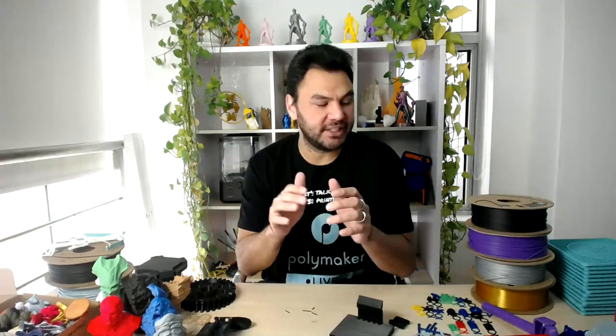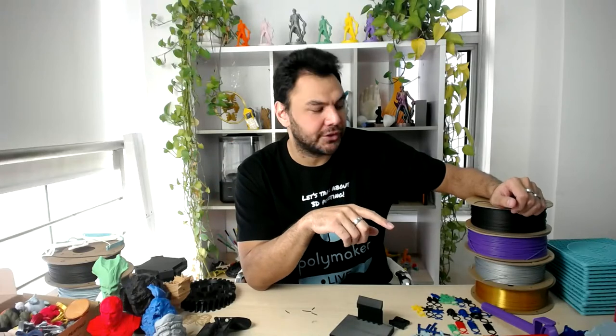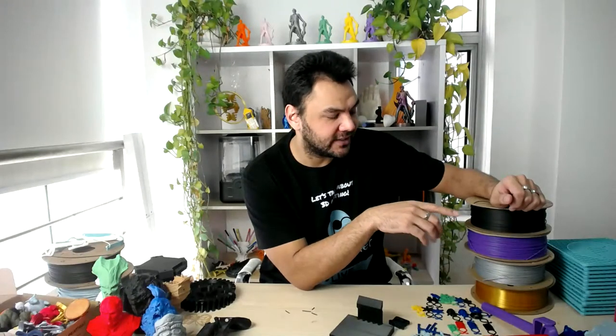Indeed, you shouldn't have a problem this way, but that highlights one point of 3D printing material, which is that depending on which dye you are using, it may slightly affect the extrusion rate. When I say slightly, it shouldn't be more than a 5 degree change in your printing temperature. Why? Because it may affect the melt index. That's one part of our quality control. We always make sure that we stay within a certain range for all our colors, because we don't want people